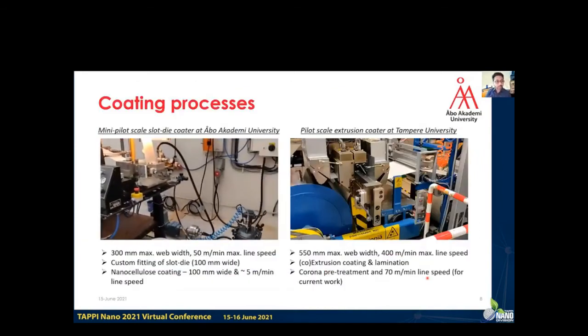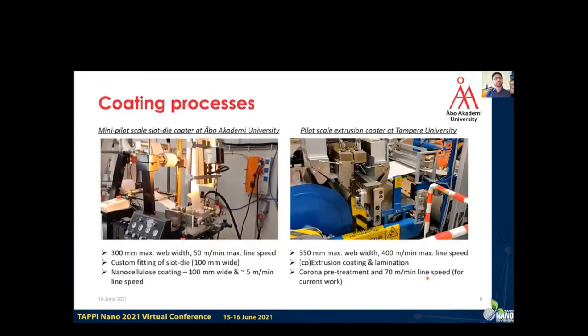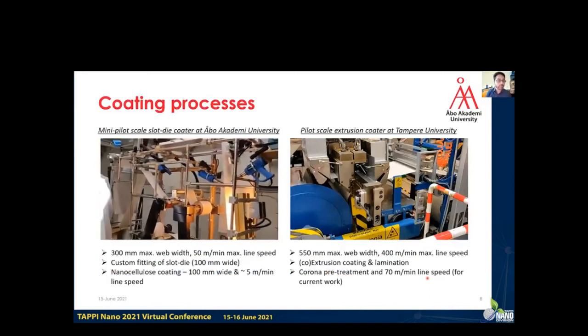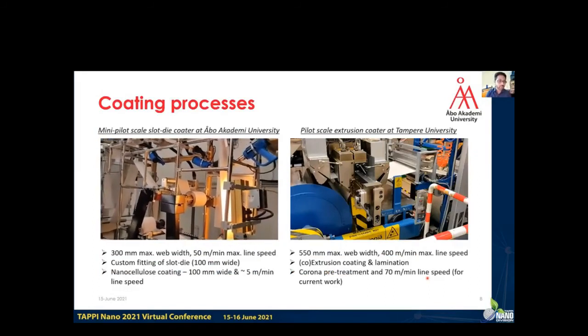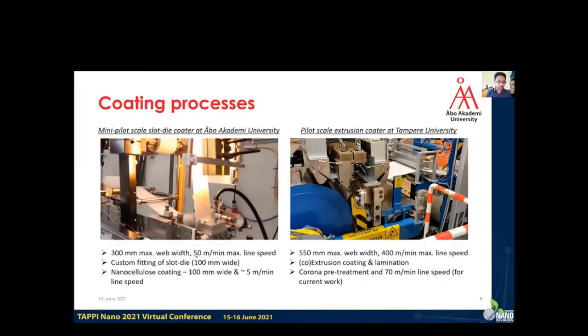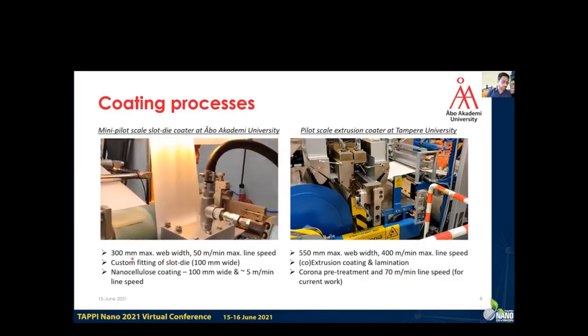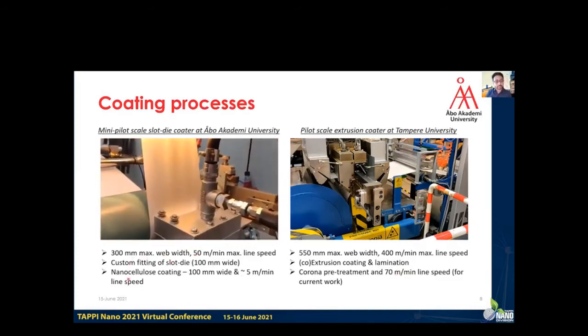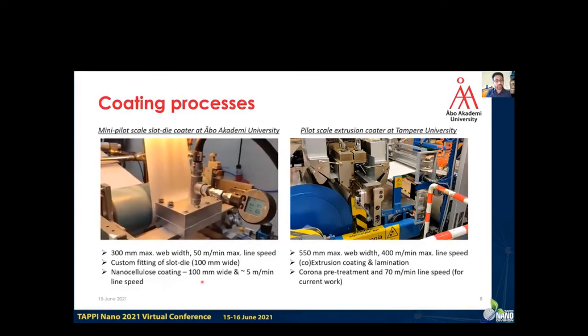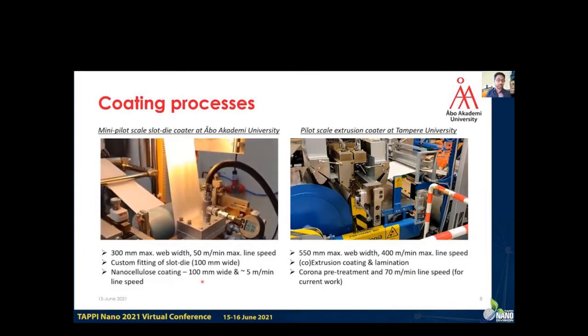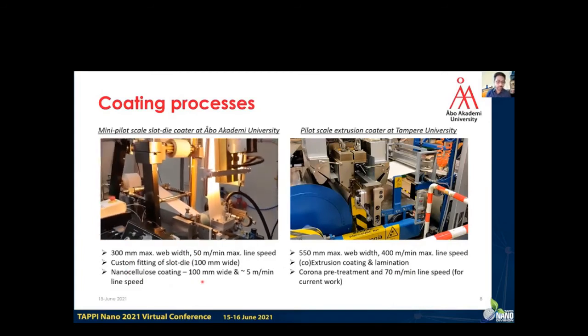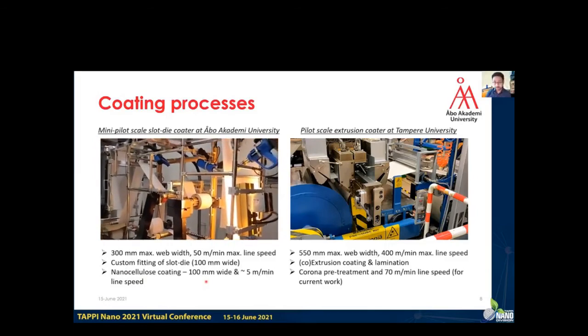So coming to the coating process, the slot die coating was done at Åbo Akademi University using a mini pilot scale coater. It has a maximum speed of 50 meters per minute and can coat up to 300 millimeter wide webs. For this work, we have a custom fitting of slot die and coatings of 10 centimeter width and 5 meters per minute line speed.